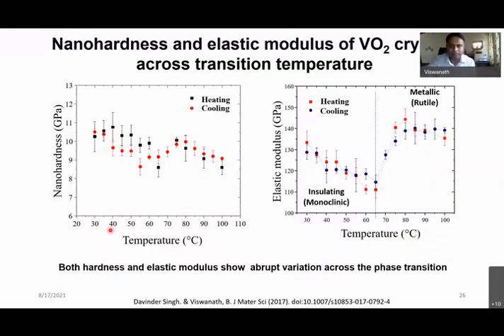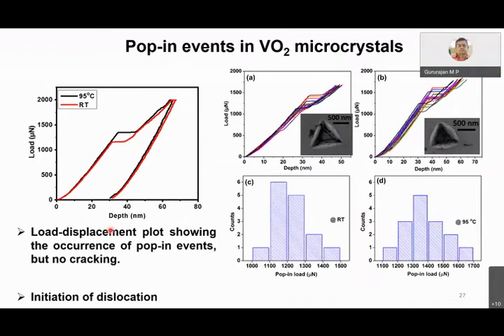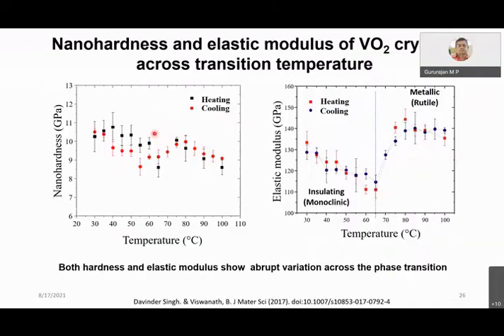So Vishwa, is the orientation relationship known between the two phases, tetragonal and monoclinic? Right. The complete orientation relationship, there is an excellent paper on it. 011 of monoclinic goes to 110 of the rutile matrix and so on. There is a nice paper. The orientation relationship is known.